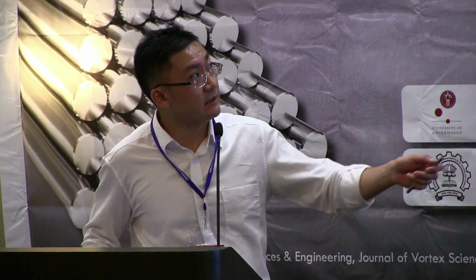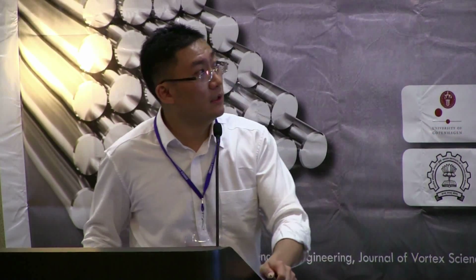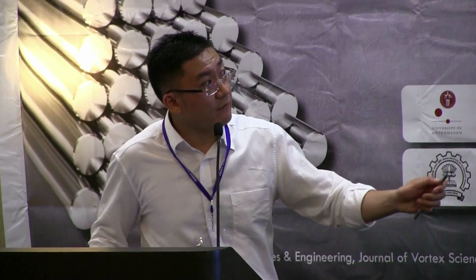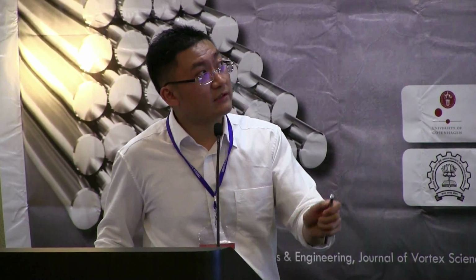And from here you can see that palladium to platinum 3:1 molar ratio gives the highest performance compared to the other concentration ranges. And the IF over IB is the poisoning tolerance, which tells how stable the catalyst is. From here you can see that the Pd1 to Pt0.3 is more tolerant, more stable compared to the other two alloys. And this one is the onset potential.